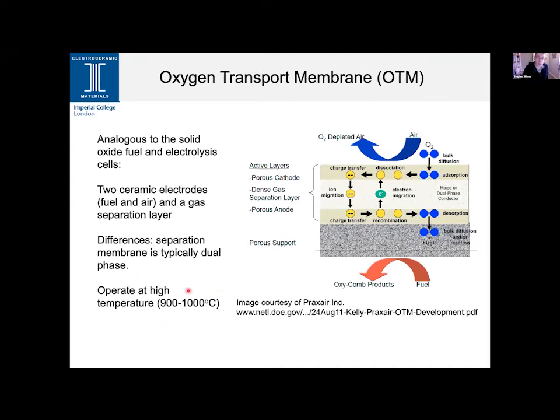So our studies of these materials have effectively focused on this higher operating temperature regime. And this is essentially the device that we've been looking at. So this is an image courtesy of Praxair in the US, where again, we're looking at this oxygen reduction process on the air electrode, charge transfer reactions, and then ion migration through the separation membrane. And our focus really is on the effect of humidity on the reactions on this air electrode side of the device.